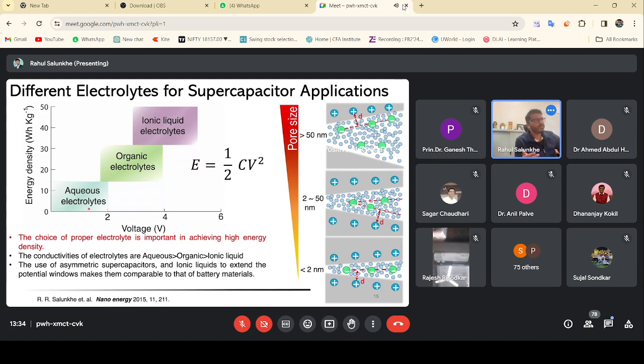Whereas with organic electrolytes, we can go up to 4 volt, and with ionic liquid electrolytes, this is the ideal case I am telling, up to 5 volt is possible. So the choice of a proper electrolyte is very important in achieving high energy density. As for conductivities, aqueous electrolytes have very high conductivity compared to organic electrolytes or ionic liquids.